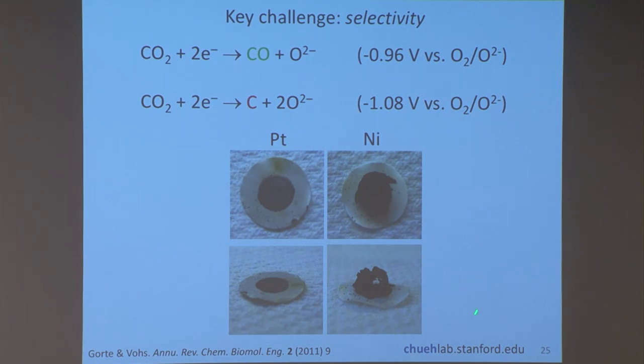This is the example from the University of Pennsylvania. On the left, it's a platinum-based electrode, which does not catalyze the second reaction, but only the first one. So the cell after reaction looks intact. But on the right, this is what happens when you do it on nickel, which is very good for the second reaction. It's also very good for the first reaction. So it's good at taking CO2, turning into CO, but it's also good at taking CO2, turning into carbon. And then you see this puff right here, that's carbon. So imagine that in your electrochemical cell. It will lead to an immediate failure.